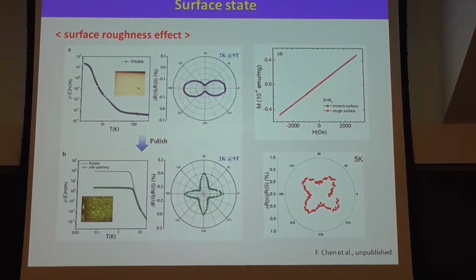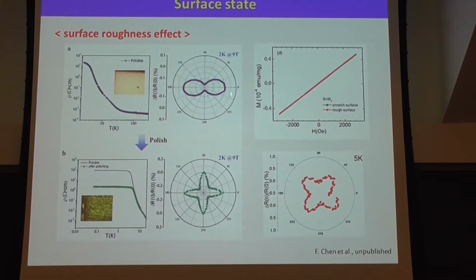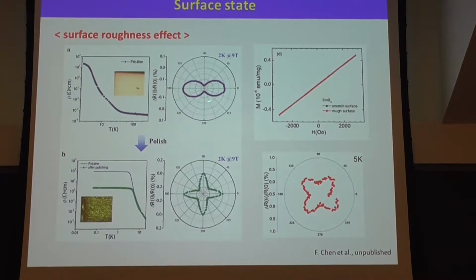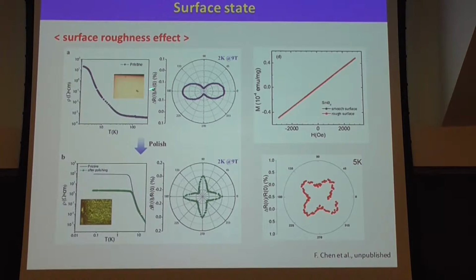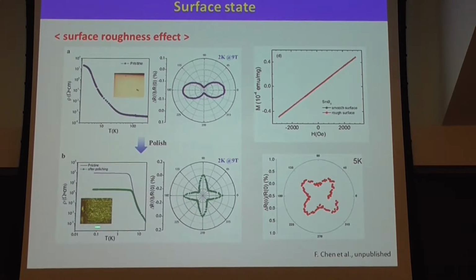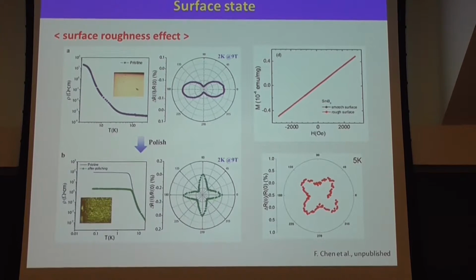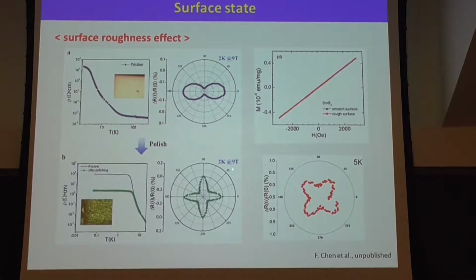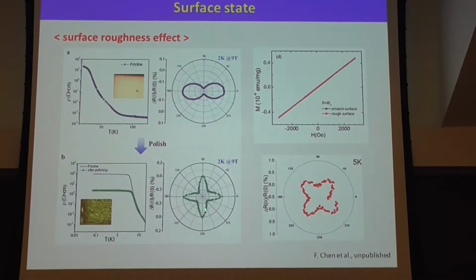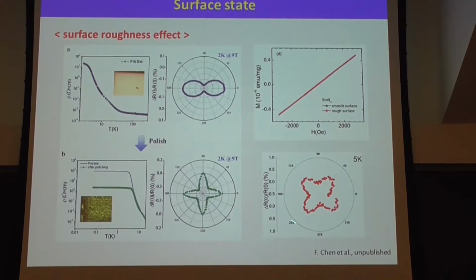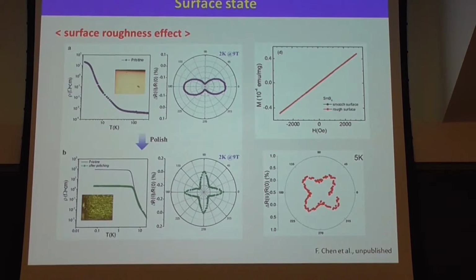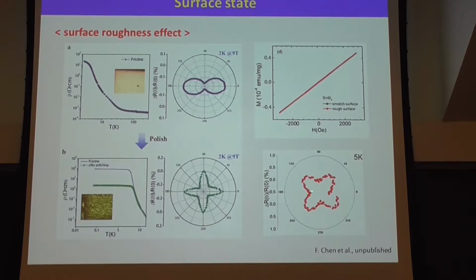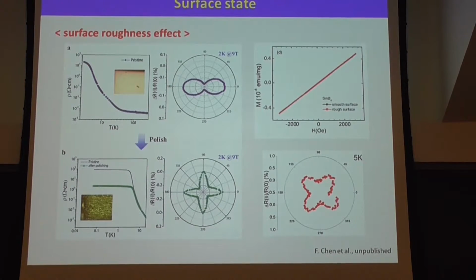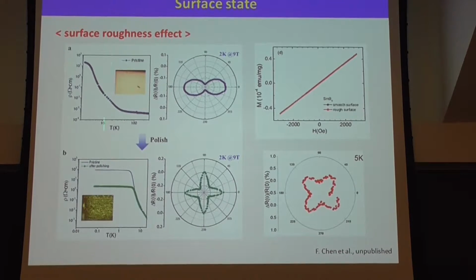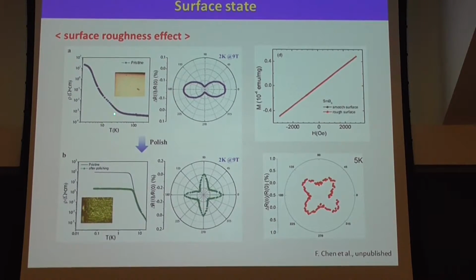Okay. Another thing is the surface roughness effect. This is for a good, high quality sample. I just show you below 4 Kelvin. This is the magnetic resistance with twofold symmetry. But if, for the same sample, we polish the sample and make the roughness okay, then this changes. This is also at 2 Kelvin, but the twofold changes to fourfold. And compared with the anisotropic magnetoresistance above 5 Kelvin, the phase is also shifted 45 degrees. Okay, right now we also do not understand why the surface roughness can change this.